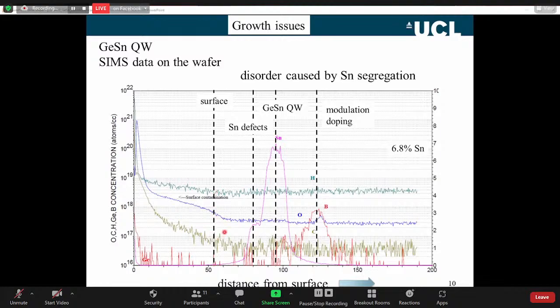We've got some oxygen in here, about 10 to the 17 of oxygen. We've also got boron. Now we know we've got boron because we intentionally put it in there. So the boron is the doping. You can see it's quite low here and just peaks where we put in the modulation doping. So the boron is actually quite good as modulation doping. It doesn't extend out too well. This region is the quantum well here, and this is the tin composition on the second y-axis on this side. We can measure the tin composition. More importantly, you can see a second tail here on the tin composition, and that's because the tin doesn't get incorporated in the lattice. It likes to surface segregate. So it produces this, let's call it a disordered defect region close to the surface.